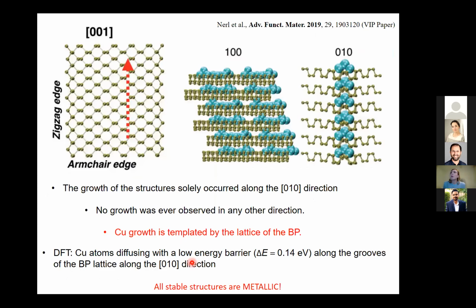So we partnered with our colleagues who do DFT, and they basically helped us a lot in computing what was the most stable structure, understanding what was going on there. And basically what we understood was the structures effectively were only observed when they were built along only one direction, and never did we experience any other growth from any other direction. So it was always growing from these grooves in the structure of the black phosphorus. So it was the black phosphorus really templating this growth across these grooves here.